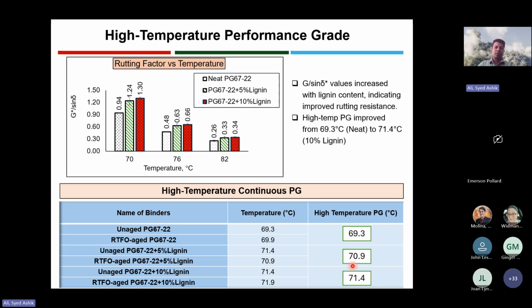At the same time, we tried to find out how much impact lignin could have on the high temperature continuous performance grade. For PG 67-22 binder, the continuous performance grade was 69.3 degrees Celsius. With the addition of 5% lignin, it increased to 70.9 degrees. And when we added 10% lignin, it increased to 71.4. So we can expect around 2 to 3 degrees Celsius increase with 10% lignin. But with 5%, not much, maybe 1 to 1.5 degrees Celsius increase.